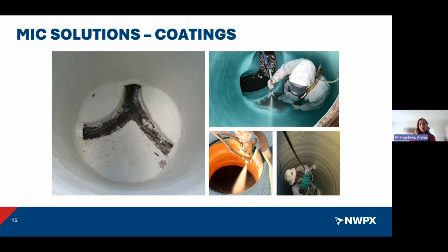We've heard where the spray-on coatings start failing in 2 years. Sometimes they last 20 years. Some municipalities had really good experience, and some municipalities had really bad experience. And we're hearing that it's not about what kind of material you use, but who the applicator is, right? How well you prepare the surface. Do you dry it well? Most of these types of coatings need a bone dry surface, otherwise it's not going to adhere. And this type of coating or rehabilitation relies on chemical adhesion between the existing wall and the lining.